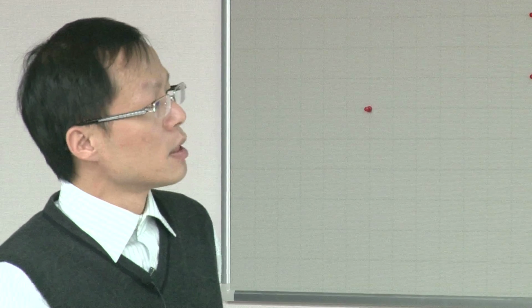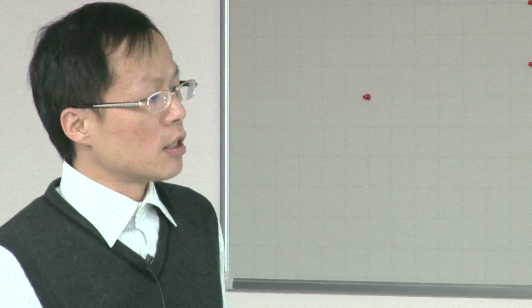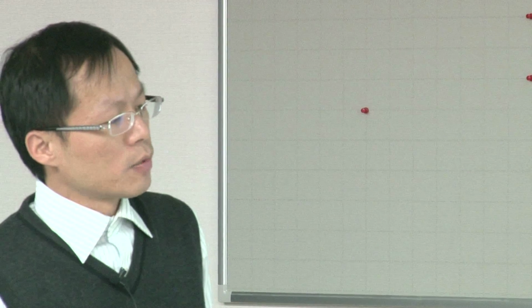Okay, and if this hole is created at the 2p level, then in the 2p orbital you could have 2p 1/2 or 2p 3/2. Let's look at this one. If the hole is at 2p, n is equal to 2, L is equal to 1, and S is equal to 1/2. So now the J value could be 1/2 or 3/2, because the total J value, L plus S, is 3/2, and L minus S is 1/2. So the J value could be 1/2 or 3/2. And so this is 2p, so we write 2p sub 1/2 or 2p sub 3/2. And for 2p, this one is L2, and this one is L3.